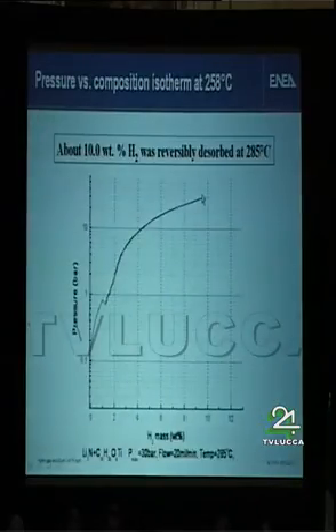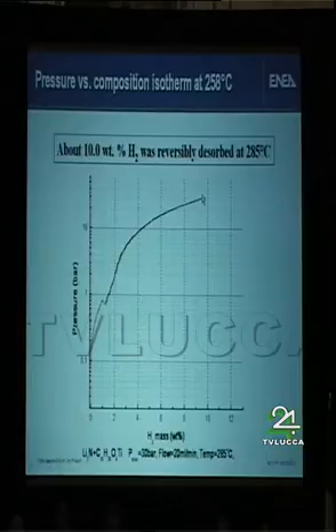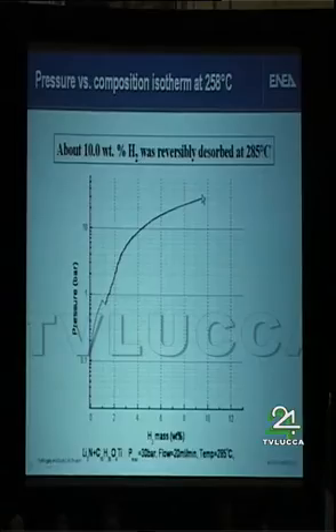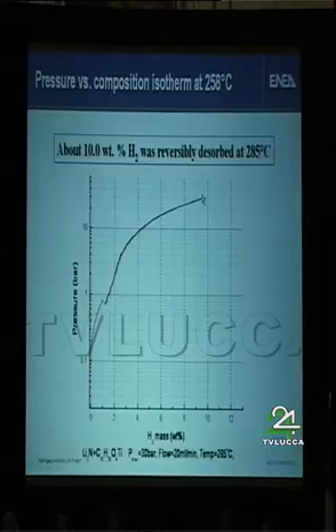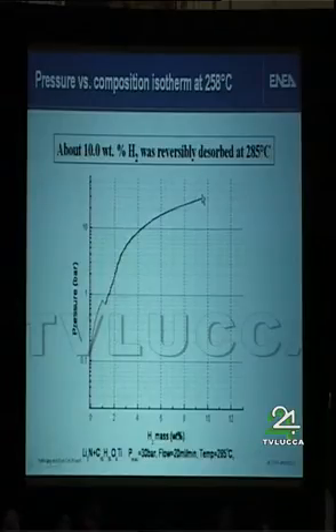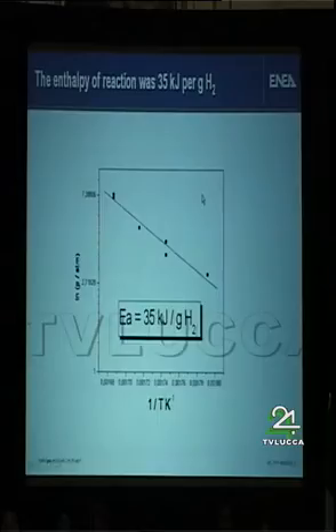This graph shows the pressure as a function of hydrogen content for the titanium-doped material. The pressure in charge was about 30 bar, and the temperature was about 285 degrees, both in charge and discharge. So it could be a good material to meet 9% weight percent for the system. The problem is that it has a very high enthalpy. The enthalpy of the reaction is very high, about 35 kilojoules per gram of hydrogen.